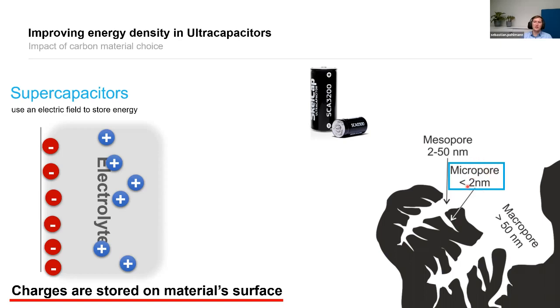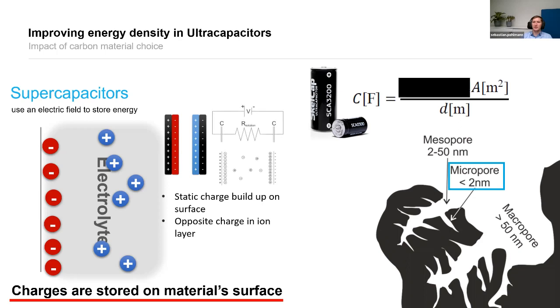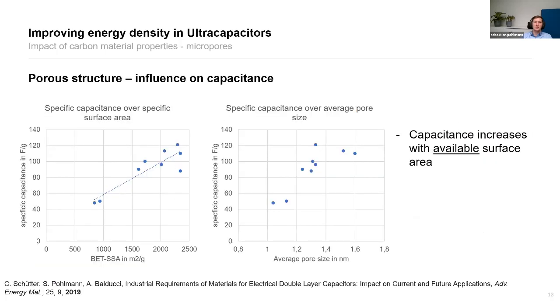They are called micropores, although they're in the nanometer range, which is always a bit confusing, but that is the nomenclature. They are under 2 nanometers, and that's really where most of the energy storage happens. All the other pores are rather transportation ways to the micropores. So they definitely impact the performance, but they do not impact that much the capacitance of the carbon. And what you want to do is, of course, to increase the surface area available to these ions.